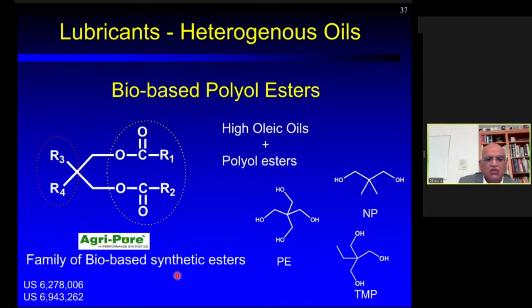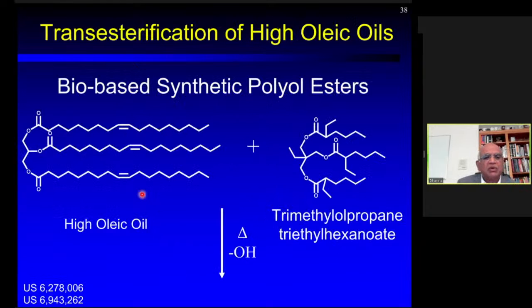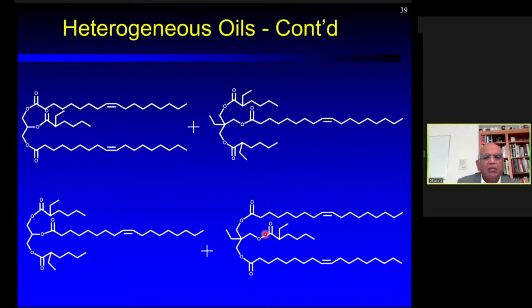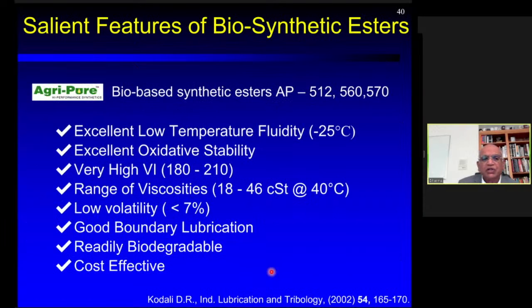These products were cost effective and they were commercialized. The chemistry that goes on is given with the example of taking a high oleic oil, transesterified with the trimethylolpropane triethylhexanoate under basic conditions at higher temperatures, which creates a composition having different head groups, as is shown here, and heterogeneous chain lengths and branched chains, as well as a little bit less unsaturation. Most of the chains are saturated. Therefore, we created a family of synthetic esters called AgriPure esters.